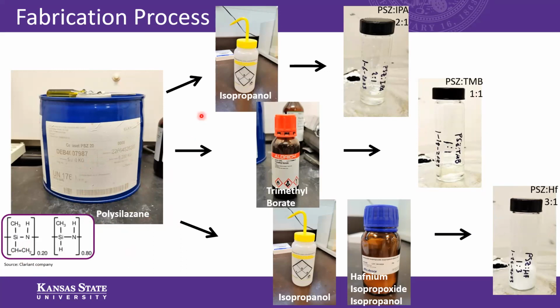So for the SiCN ceramic path, we took polysilazane and isopropanol in a 2-to-1 ratio. The main reason for using isopropanol in this case is to be used as a solvent, which will dilute the precursor and ensure optimal viscosity when coating carbon fibers.